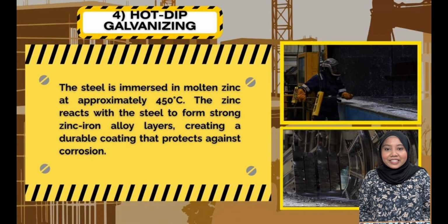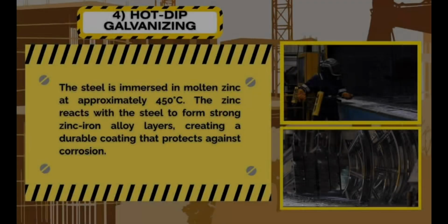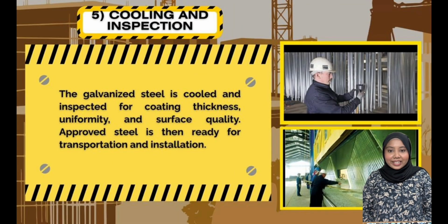The steel is then immersed in molten zinc at approximately 450 degrees Celsius. During this process, the zinc reacts with the steel surface to form strong zinc-iron alloy layers. These layers create a durable protective coating that resists corrosion and extends the service life of the steel. Finally, the galvanized steel is cooled and inspected. The coating is checked for thickness, uniformity, and surface quality to ensure it meets the required standard before the steel is transported and installed on site.